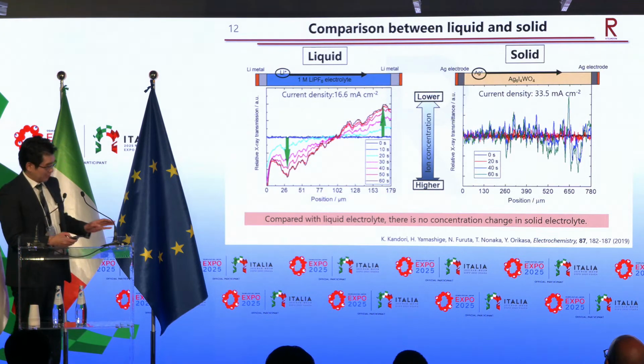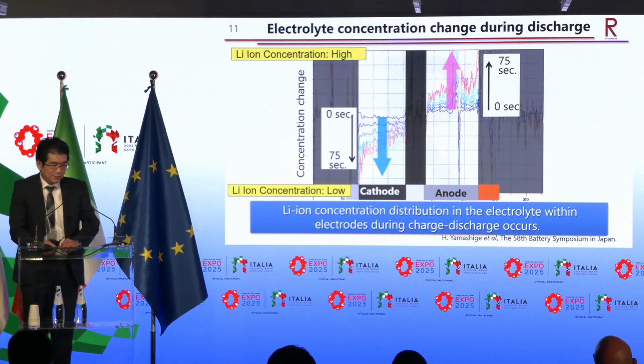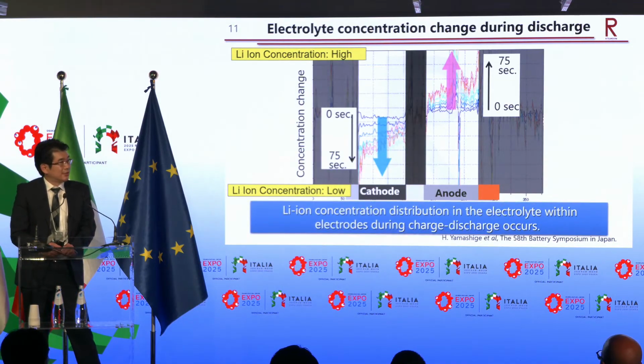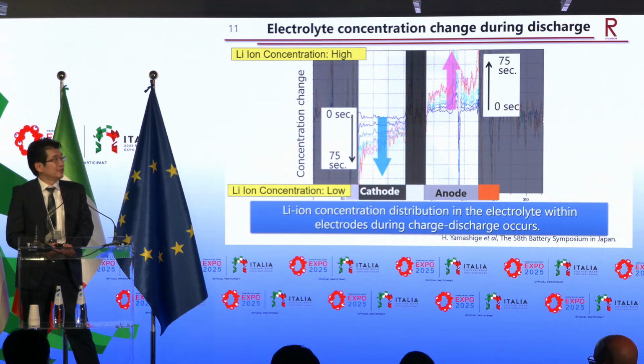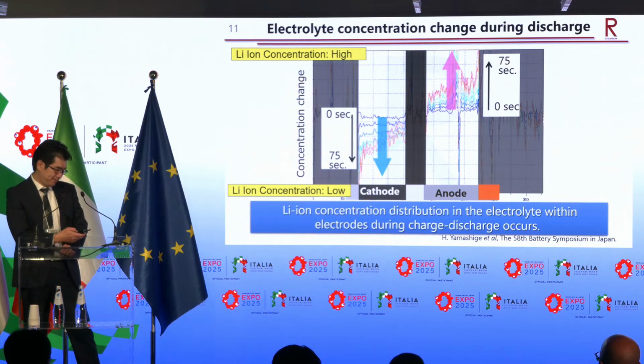So before that, this phenomenon affects real battery performance, because the concentration of lithium ion in the electrolyte changes the real ionic conductivity. So in some parts, the ionic conductivity is much lower than in other parts. So this decreases the charge-discharge capability.